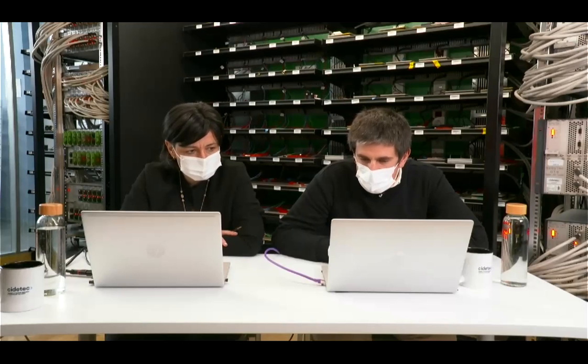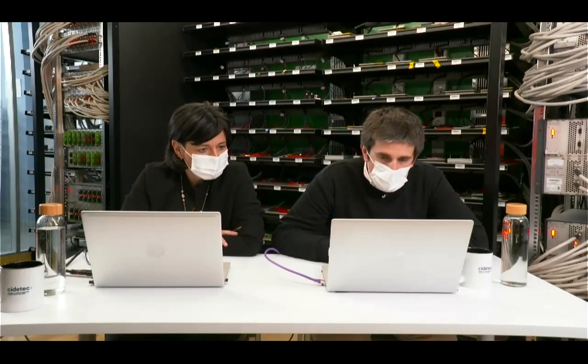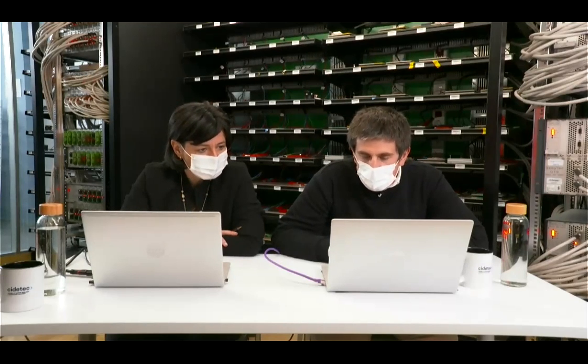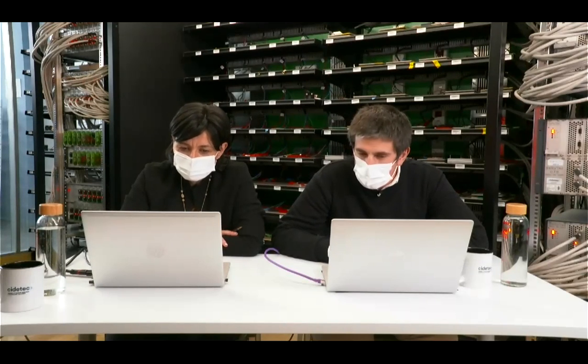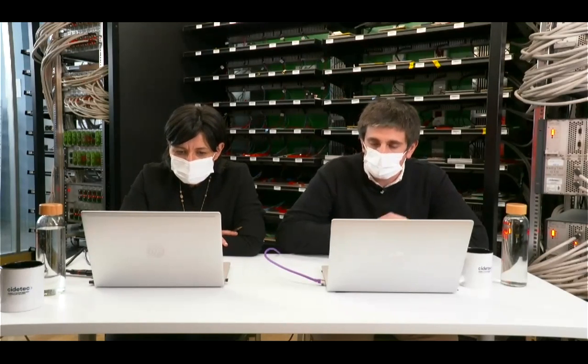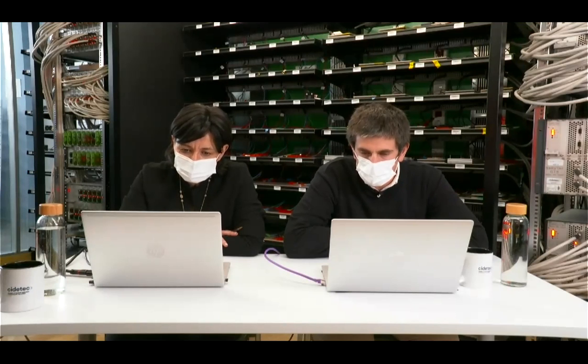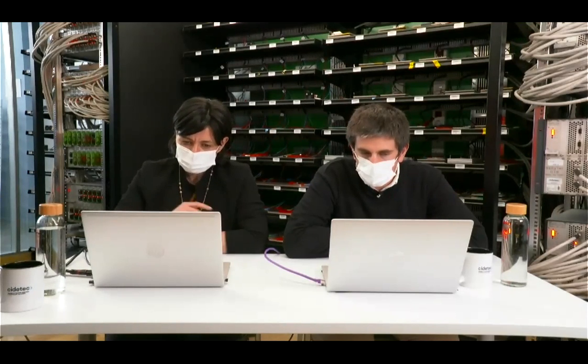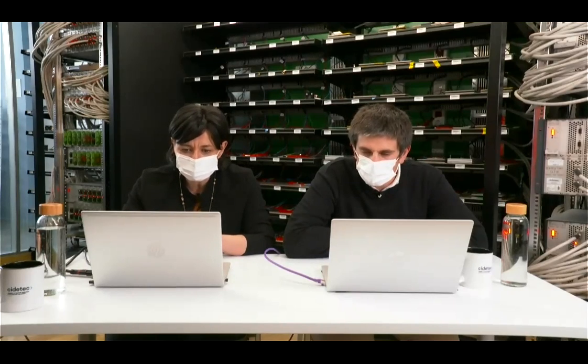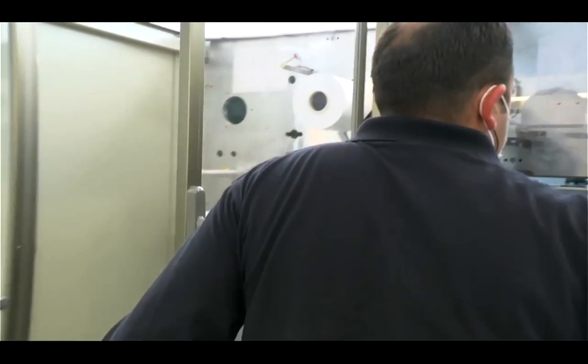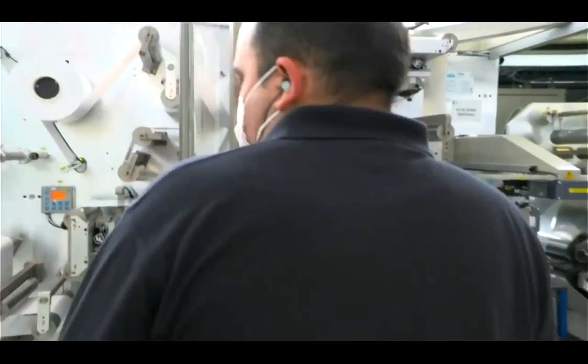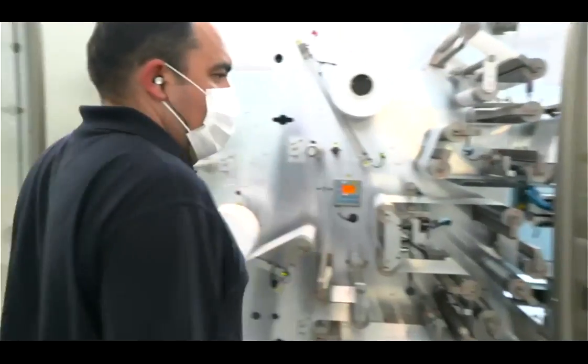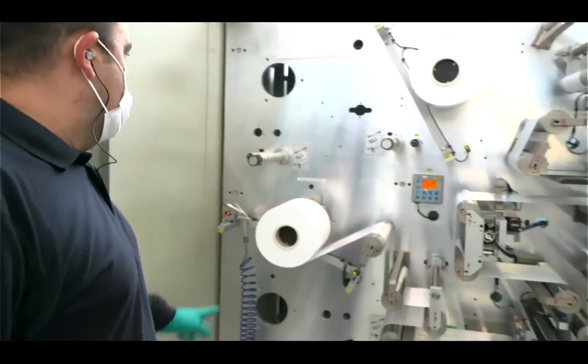So also concerning this stacking and winding machine, there is a question about what separator we are using. Actually, as I mentioned before, our stacking machine is limited to laminable separator. The separator must have a very thin layer of, in general, PVDF, or a very thin layer of an acrylate.